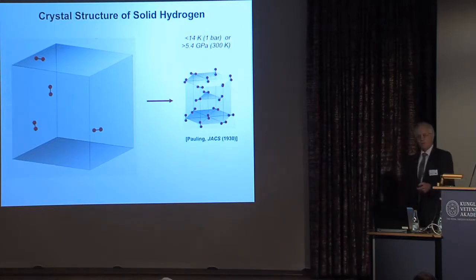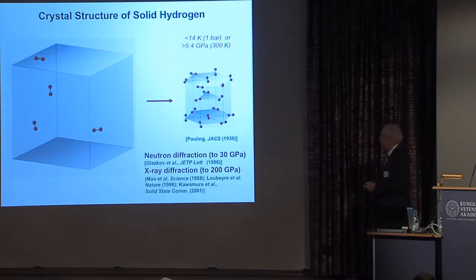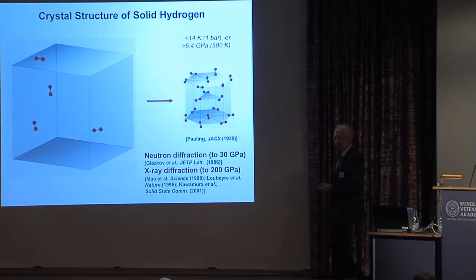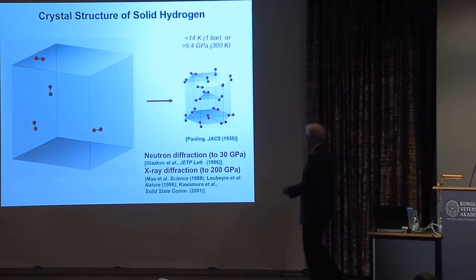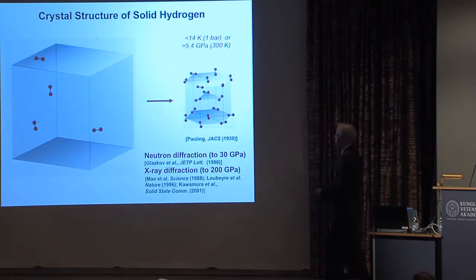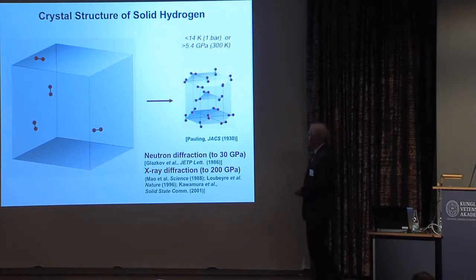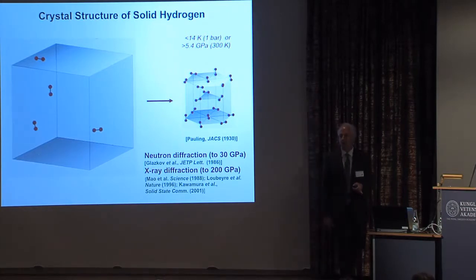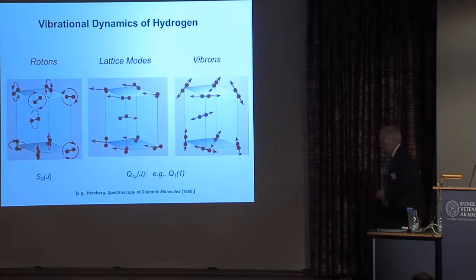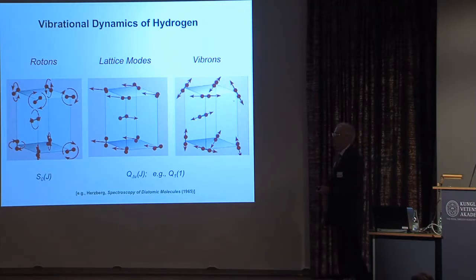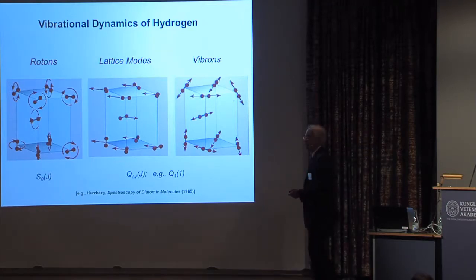What we now know from diffraction studies, despite the difficulty of studying hydrogen by diffraction techniques, both X-ray with only one electron per atom and neutron scattering, which is very weak in comparison to X-rays, is that this particular structure under a range of temperatures persists to at least 200 gigapascals, and this is what we call phase one. Well, most of our studies of hydrogen have come from spectroscopic studies, that is, studies at very high pressure as a function of temperature.